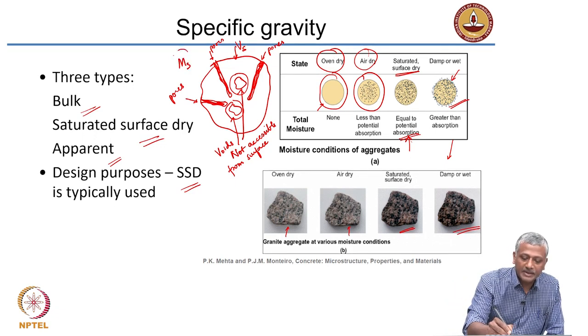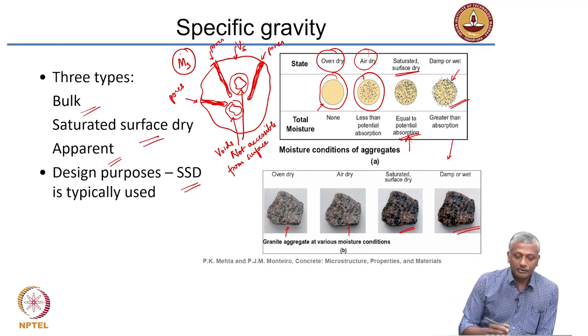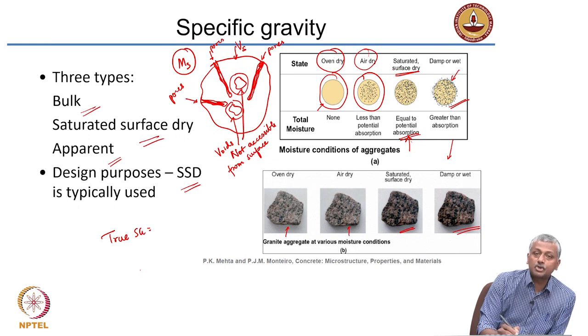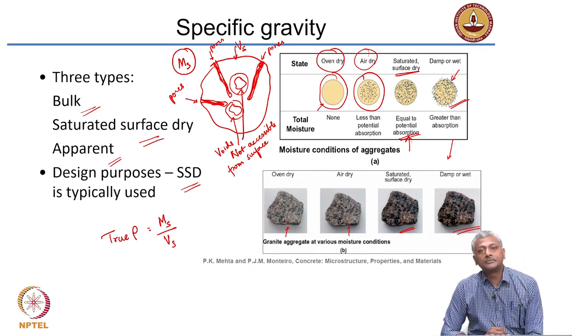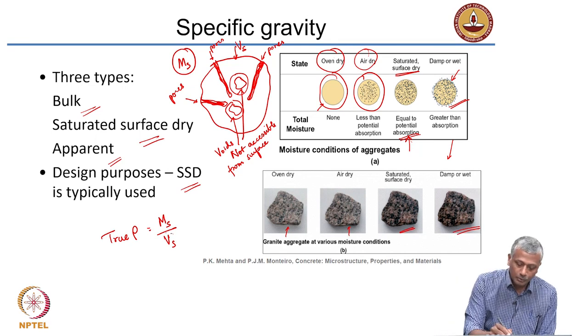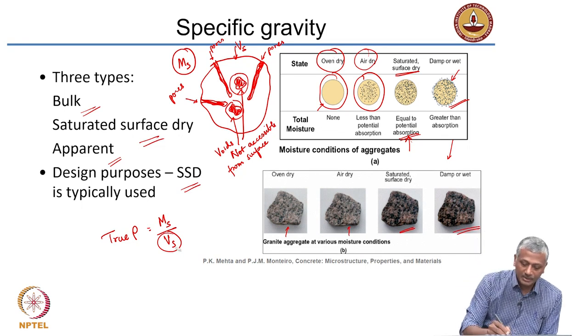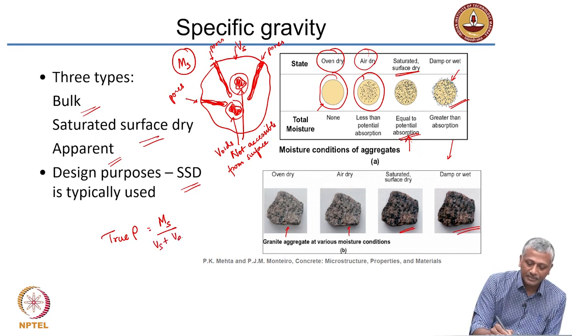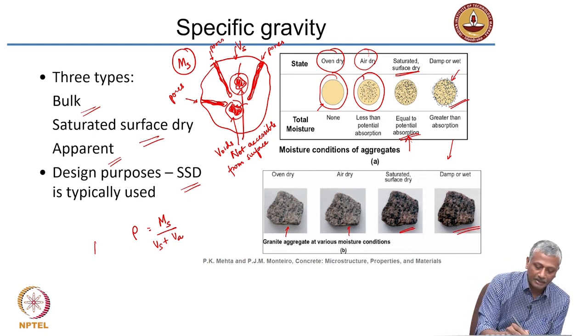The true density would equal the solid mass divided by the solid volume. However, we can never determine the true solid volume because the voids inside which are inaccessible from the surface — we can never determine their volume accurately. In most cases, you will get solid volume plus the air volume filled inside those inaccessible voids. That is why we do not call it true specific gravity — we call it apparent density.